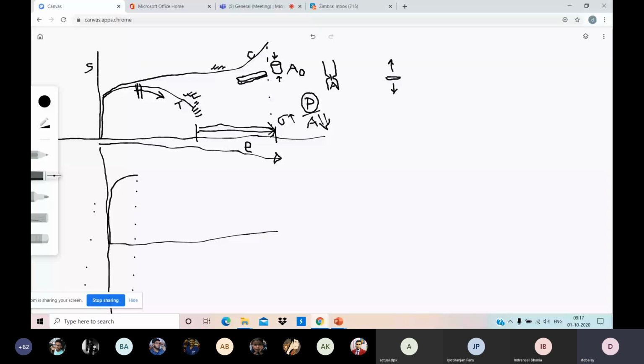Who can say what the other reason is that leads to failure? Yes, tell. Sir, if there is any internal crack or defect, in tensile load it opens up, but in compressive load, it closes. What is your name? Rashid, sir. Rashid, very good answer you have given. That is the right answer.